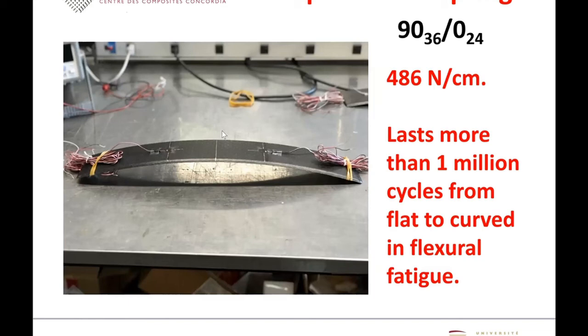Now, the important thing is that people may say, okay, fine, you can deflect that, but can it last? Can it really fluctuate up and down a lot? So what we did is that we pushed this up and down from a curved configuration to flat, 1 million times. Okay, 1 million cycles, up and down, from curve to flat, and it did not fail. After 1 million cycles, it's still running okay, no crack, no failure.